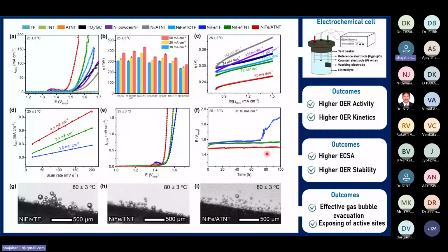To find out the reason, we used a very high definition camera to capture how bubble release happened on the electrode surface. From that footage, we observed that in the hydrophobic TF based nickel Fe catalyst layer, there was dead zone formation and accumulation regions, which actually degrade the catalyst.